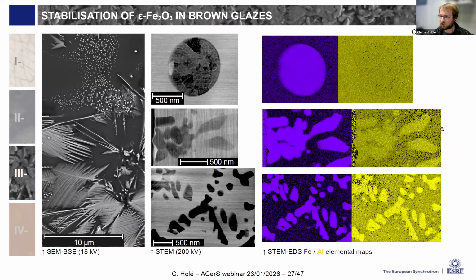So I analyzed these different structures using STEM-EDS, so scanning transmission electron microscopy. And here you can see the 3 lamellae that I prepared. And the EDS showed a very interesting feature. So of course, we have a lot of iron everywhere because it's iron oxide. But you can see that on the very undeveloped dendrites, we have basically the same amount of aluminum inside these, let's call them bubbles, and the surrounding glaze. But the bigger the dendrites and the crystallites grow, the more aluminum we can see.